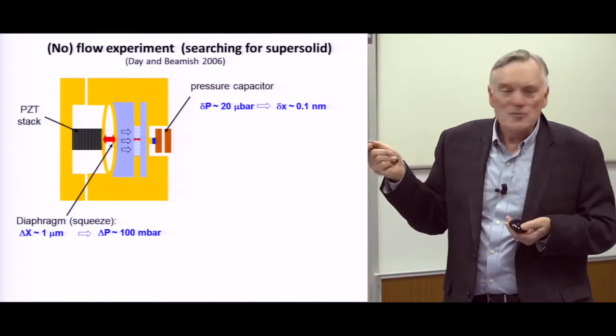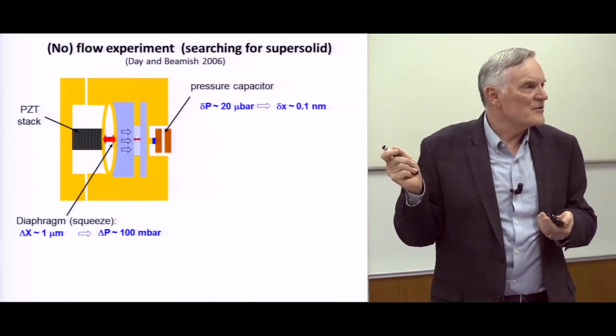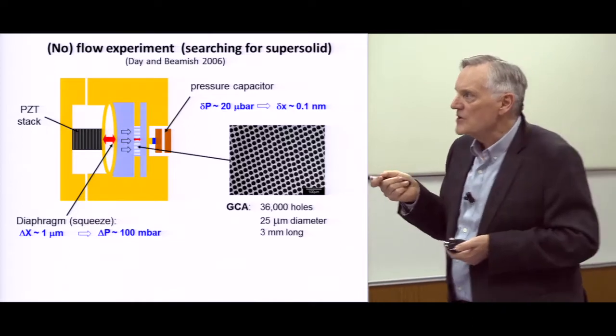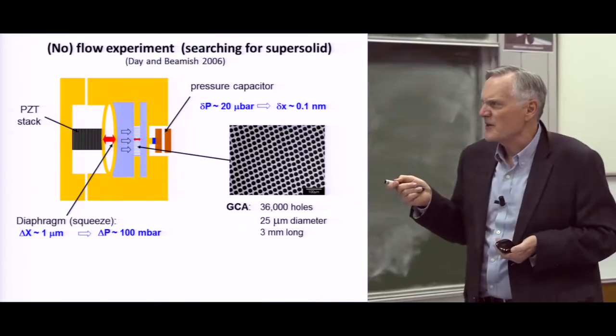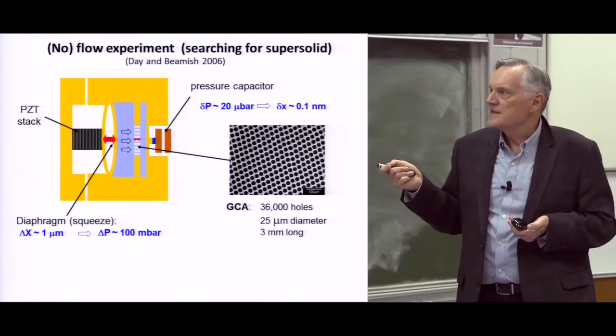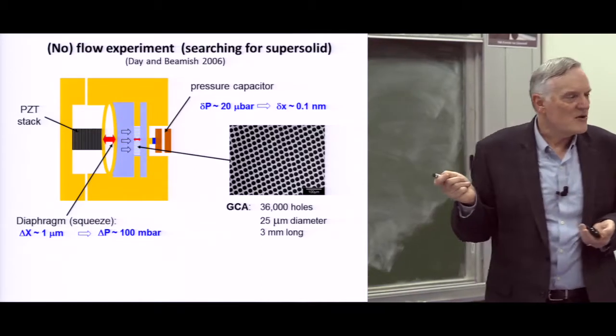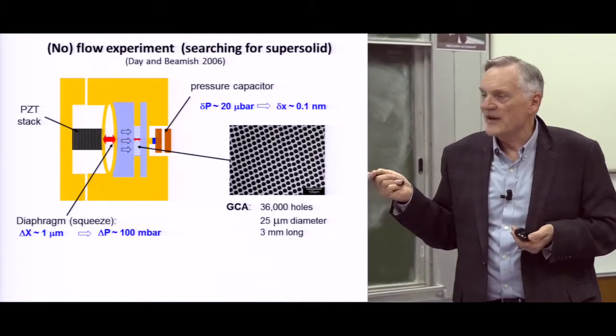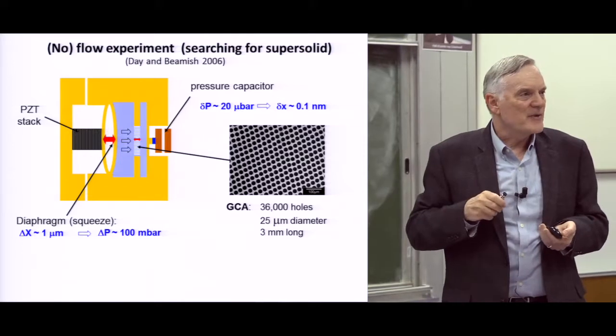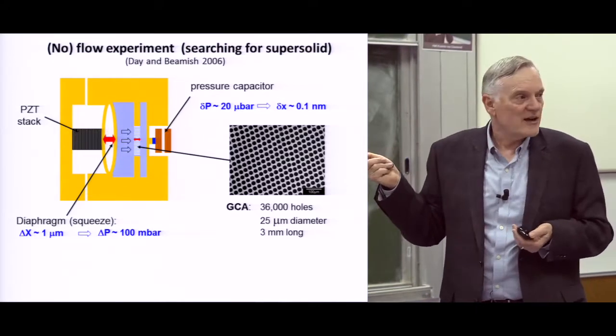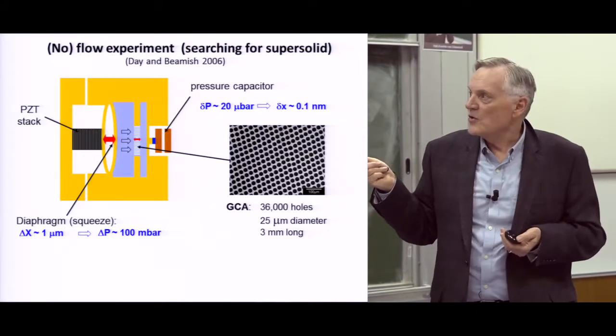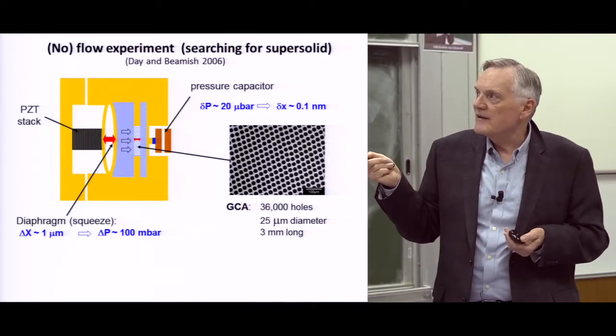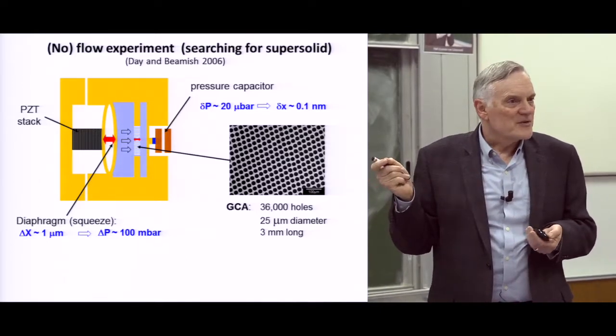In between, you put some little tiny holes to see if it flows through them between the two chambers. So the holes we chose to get lots of sensitivity are something called a glass capillary array. It's a piece of glass that had about 36,000 holes with a 25 micron diameter. The plate of glass is about 3 millimeters thick. So these are long, skinny channels, 25 micron diameter holes. So that's what's in between. So we push on this side, look on that side to see if anything comes through.